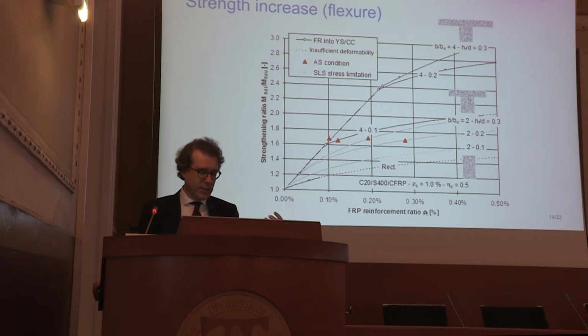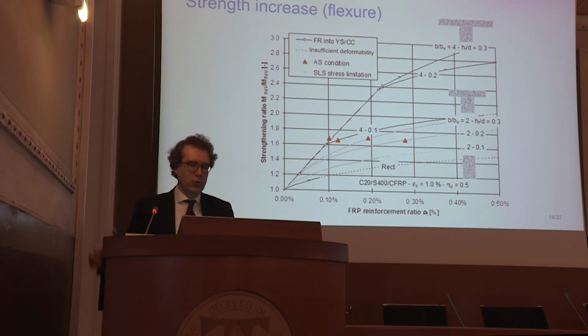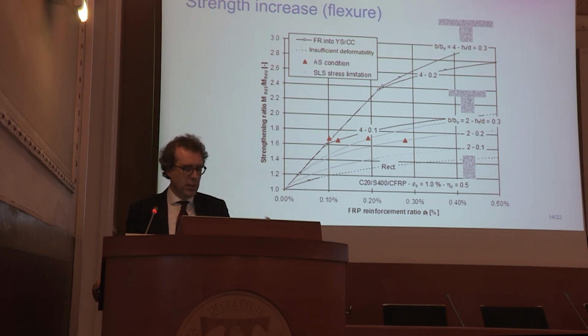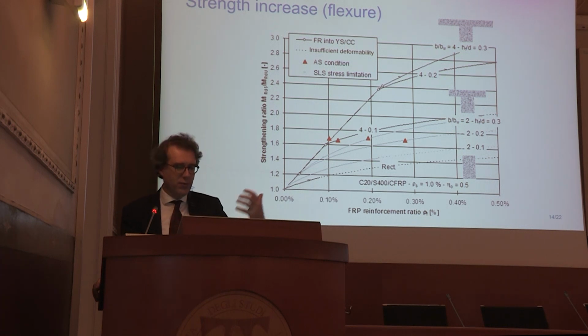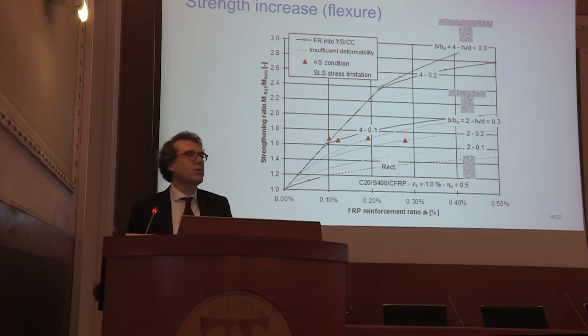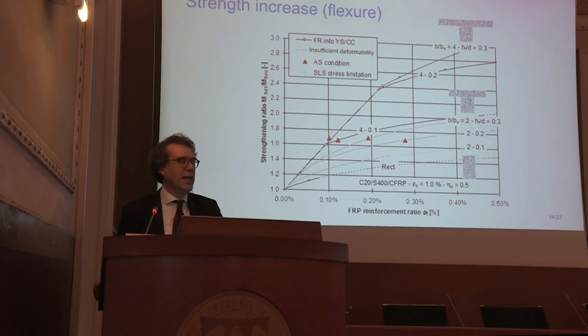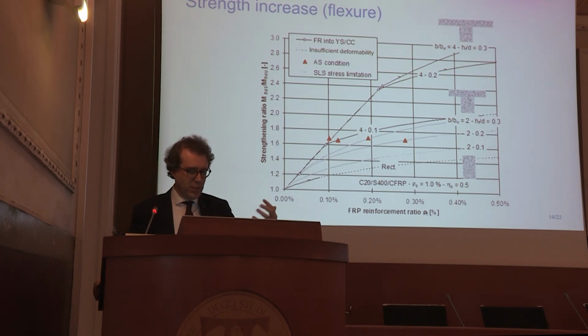And that's why this is typically a non-linear behavior. The higher you try to increase the reinforcement ratio, the effect becomes a little bit less, depending if the concrete can follow. If the concrete has a T-section, there's a lot of concrete in compression which can help, then you see it is a much more linear behavior.